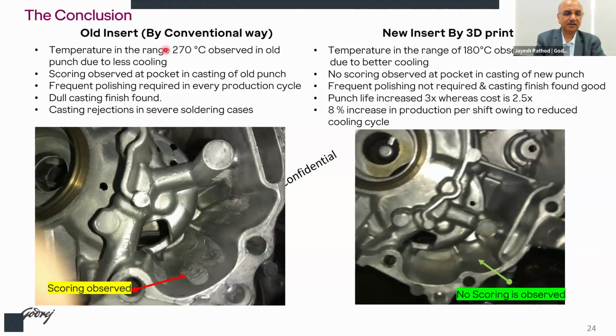So with the conventional method, there was this problem which I had indicated, and this is by using the 3D printed insert. The advantage we got was that there was no scoring observed throughout the life of the punch, and the punch life has increased by 3 times. So it was lasting till the complete die life of the entire die. And of course, there is a cost attached to it. It is 2.5 times more than the regular piece we would have made. But again, there is a minimum 8% increase in the production per shift.